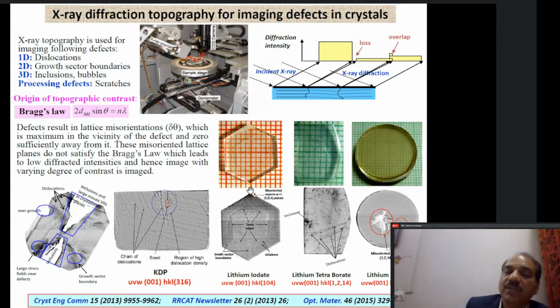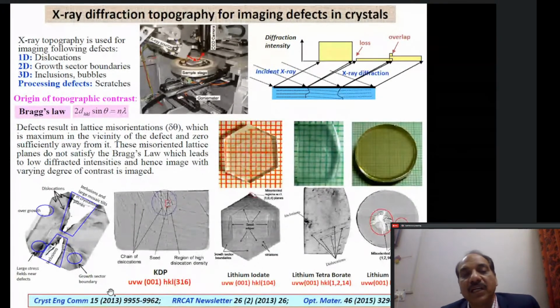So whatever crystal we grow, we subject it not only to the optical investigations, the ones which I have shown, X-ray, UV-visible, then Mach-Zehnder interferometry, then basically Bareffin's interferometry, right? We also subject them to peeping deep inside the crystal to see what the lattice distortions are, what the defects are, what the inclusions are, where the inclusions are more, where they are less, and where there are misoriented regions of those lattice planes for which we really want a device element to be fabricated.